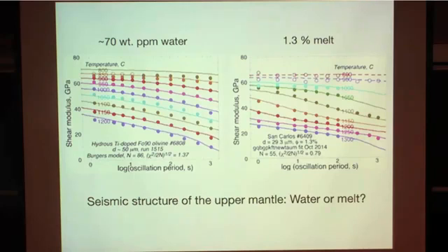So if you mean the water fugacity, yes, the equation that I showed was for the water fugacity, but you can actually convert that into concentration. What we do measure in the end, because we're at a constant pressure, we just vary, in effect, the concentration. We directly vary the concentration. This is one of the big differences to previous deformation experiments. The experiments were always water saturated, so you could only get this exponent as a function of varying the pressure.